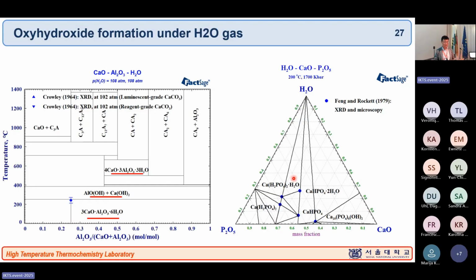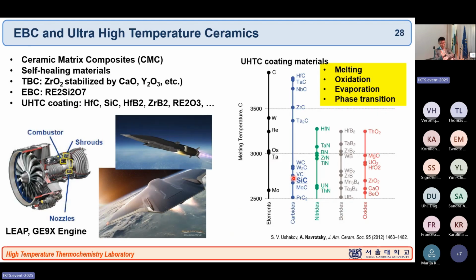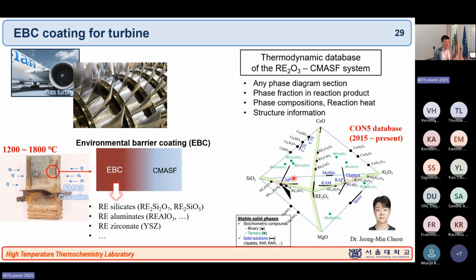And this is another example of those kinds of ternary phase diagram calculations. I have only a very short time. So let me just show you very quickly the ultra high temperature ceramic application. This is the EBC or UHTC kind of application. EBC means environmental barrier coating, which typically uses rare earth silicate phases, especially against this kind of turbine material.